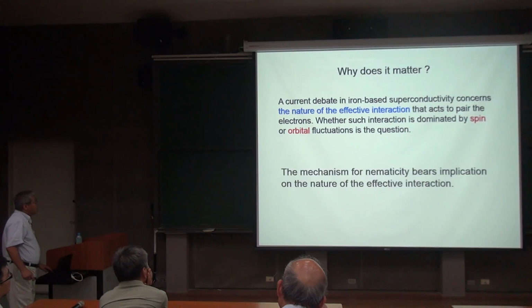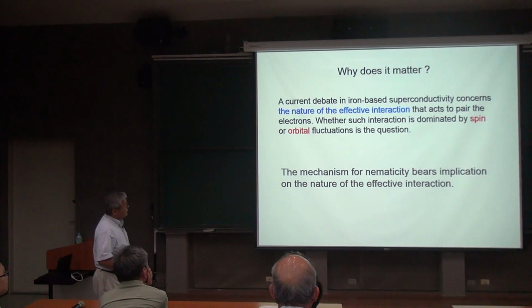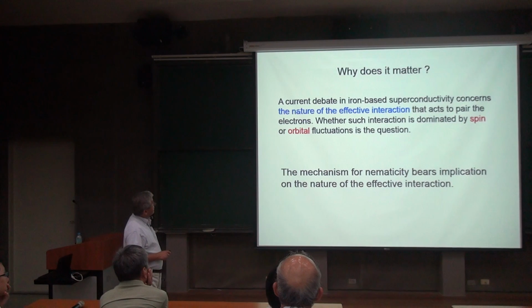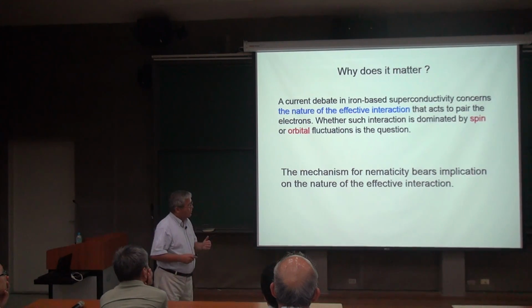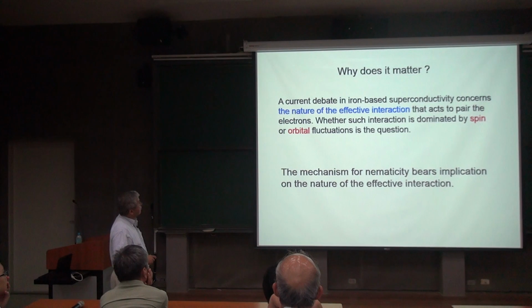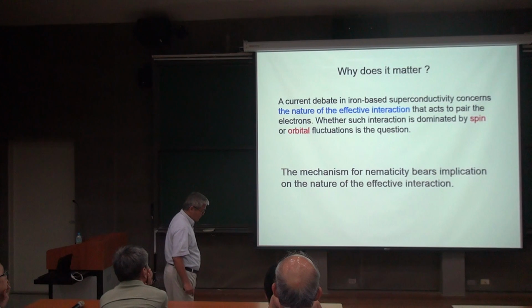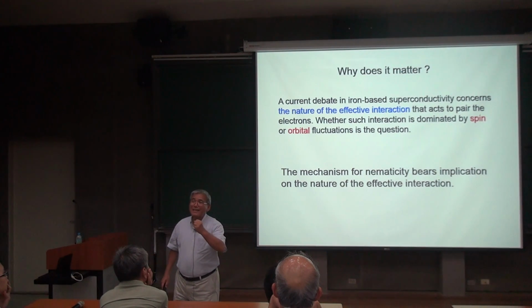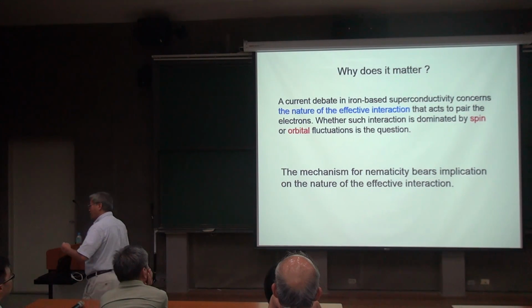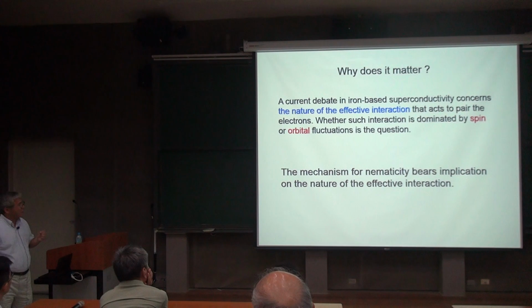So now you can see why we care about what's causing the nematicity. Suppose nematicity is proven to be caused by the orbital interaction rather than the magnetic interaction, then we know, at least we have a strong hint, that this effective interaction that we are going after actually involves the orbital degree of freedom. That's what we call the orbital fluctuation. But if what's causing the nematicity is the magnetic mechanism, the spin mechanism, then we have a very strong hint that what's causing the Cooper pairing is the magnetic interaction. So that matters. That really lies at the heart of high temperature superconductivity. That's why we care to investigate the nematicity at all.